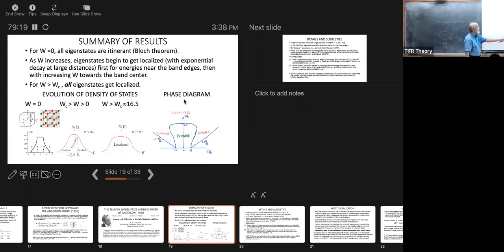And if you look at the phase diagram, you can write it as W over T versus E over T. It turns out for this model, actually, there is a well-defined band edge, because it has a sharp cutoff, which are these two lines. And then here is where the extended region is, at the center of the band, and then in the tails are localized states. And actually, this thing closes incredibly sharply. It's very flat. If you do numerics, that's how you find it.